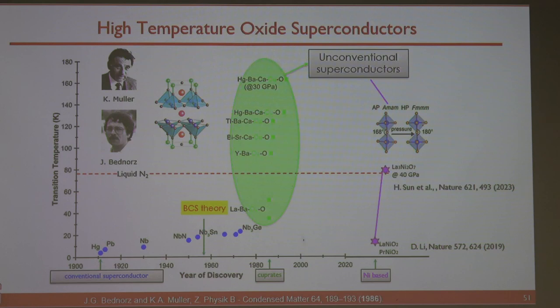And this, by the way, also comes back to the idea of Muller. Remember he said that those are insulators, very poorly screened. If you look at the dielectric in a situation of poor screening, the phonon scattering will be forward and small Q. So how could you give me the scale of the small Q? 0.1 angstrom, universal.